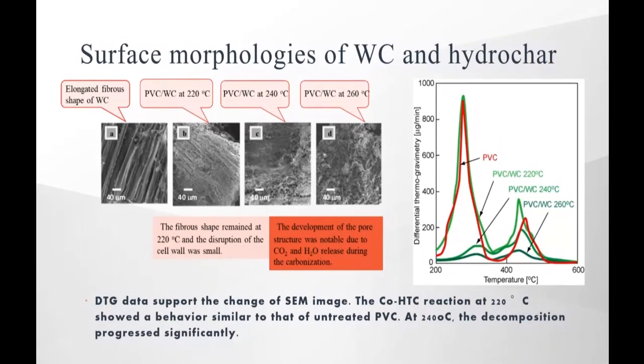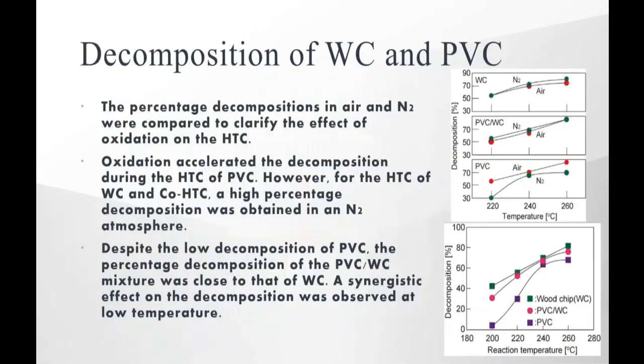The development of pore structure was notable due to the evolution of carbon dioxide and steam. As shown in the figure at the right-hand side, differential thermogravimetric analysis data supports the change of SEM image. Next, the percentage decomposition in air and nitrogen were compared to clarify the effect of oxidation on hydrothermal carbonization.